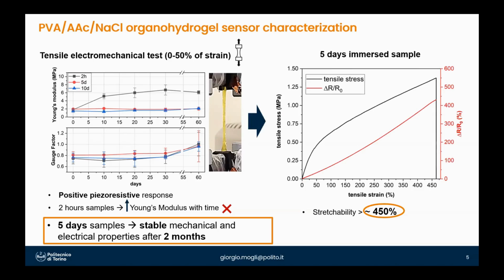And a tensile test up to rupture was conducted, showing an optimal stretchability. They were able to elongate up to 450% strain. And they showed a linear piezoresistive response, because when the hydrogel is stretched, the ions need to cross a longer path to cross from one electrode to the other.